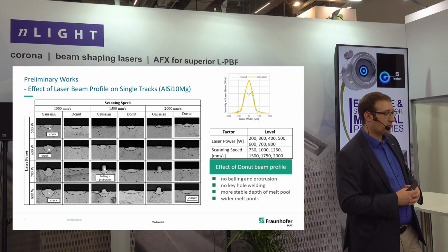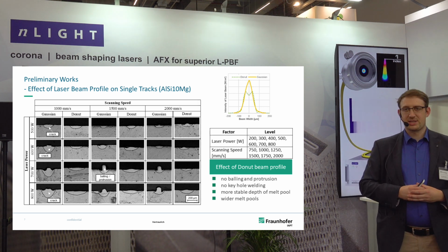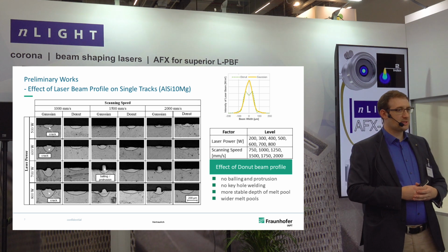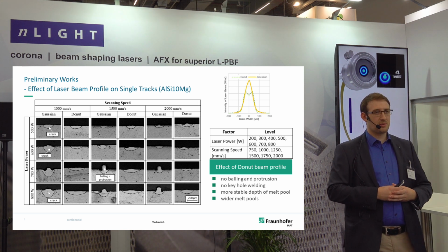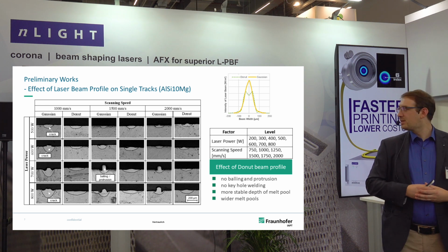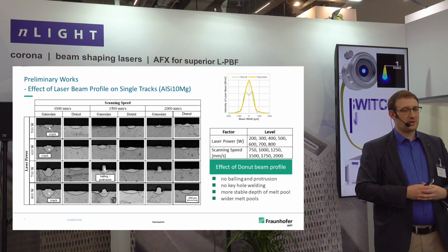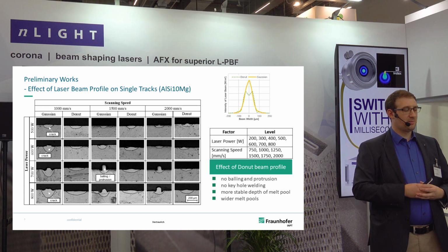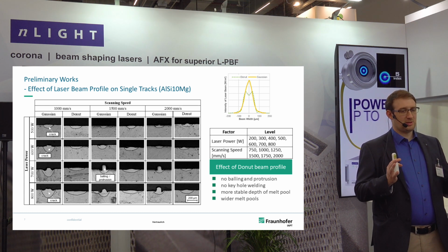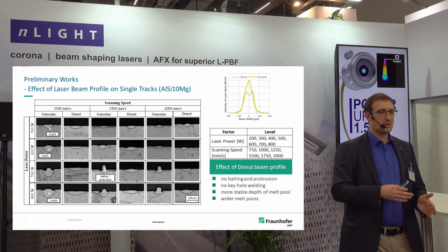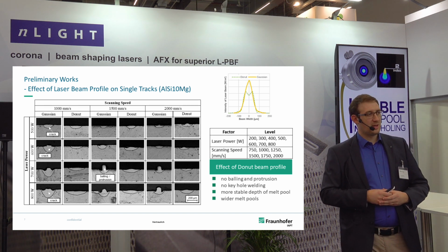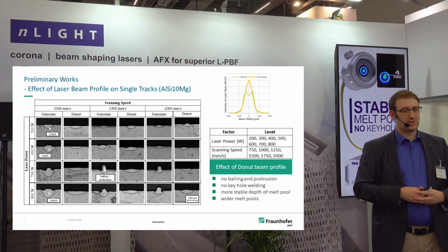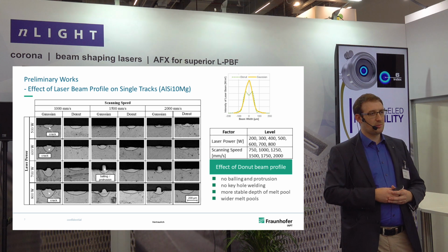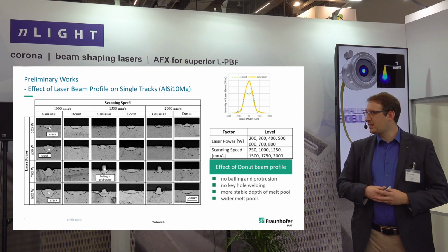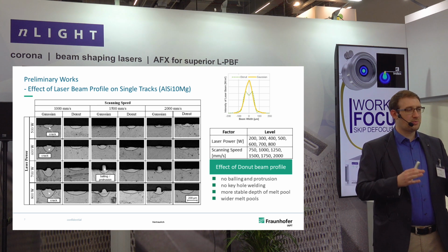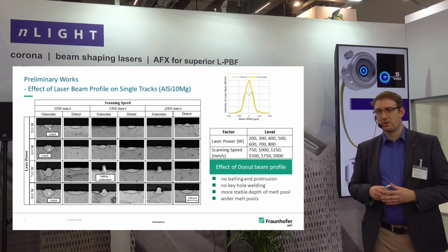What is shown here on the top right: you can see two different beam profiles we used, in yellow a typical Gaussian beam profile, and then we created a ring-shaped beam profile with the same size, the same diameter, to compare a Gaussian and a donut profile. In the table with the etched cross-section of a single weld track, you can see, for different laser powers and scan speeds, a comparison of the melt pool for the Gaussian and for the donut profile.